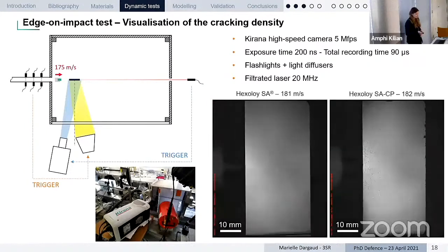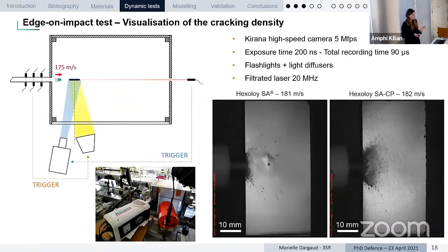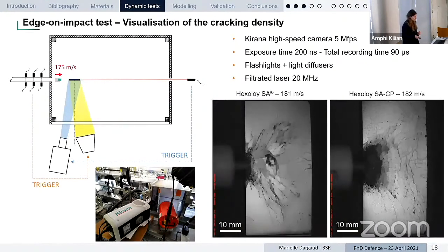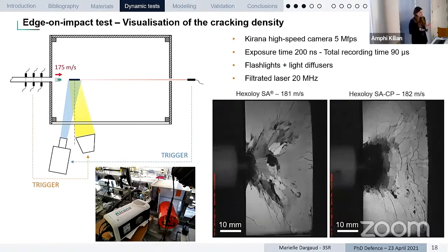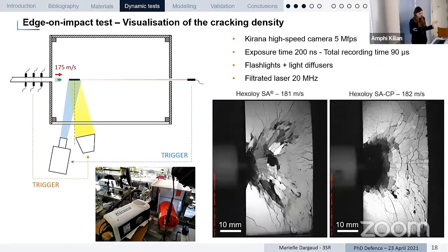The fragmentation that we see developing upon impact in the two materials is such that after 4 microseconds, the ceramic is fully fragmented. You can see here some radial cracks nucleating in the ceramic, and then some hoop cracks generated in a second time in the tile.